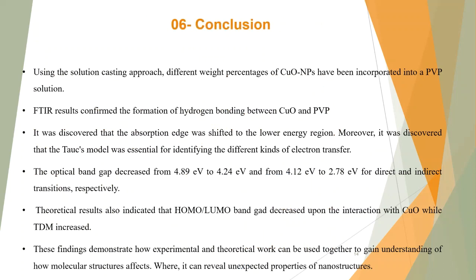Conclusion: using the solution casting approach, different weight percentages of copper oxide nanoparticles have been incorporated into the PVP solution. FTIR results confirmed the formation of hydrogen bonding between copper oxide and PVP. Also, it was discovered that the absorption edge was shifted to the lower energy region. Moreover, it was discovered that the Tauc model was essential for identifying the different kinds of electron transition. The optical band gap energy was found to decrease with increasing copper oxide concentration for the direct and indirect transitions.